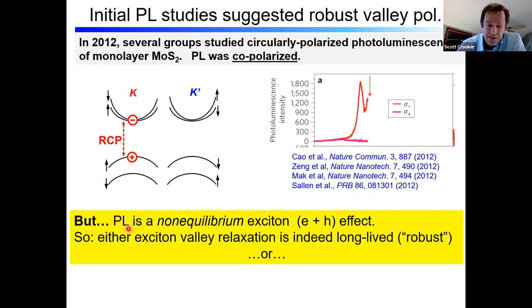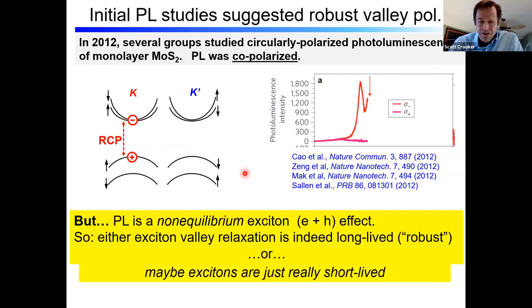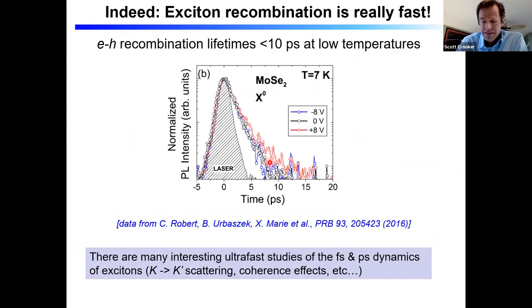But it's important to keep in mind that photoluminescence, at least, is a non-equilibrium effect. You need both an electron and a hole. So maybe exciton valley relaxation is very long-lived or robust. But maybe excitons are just really, really short-lived. That is, they recombine even faster than any relaxation processes take place. And in fact, that latter proved to be true. Exciton recombination in these materials is ridiculously fast, just a few picoseconds. And so there are many interesting ultrafast studies of femto and picosecond dynamics of excitons in these materials.